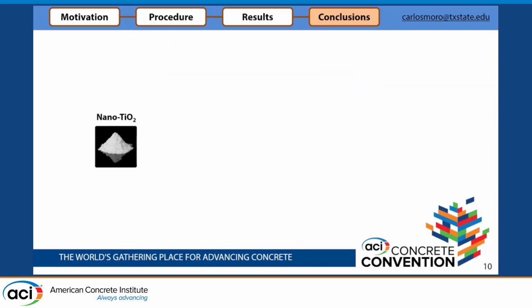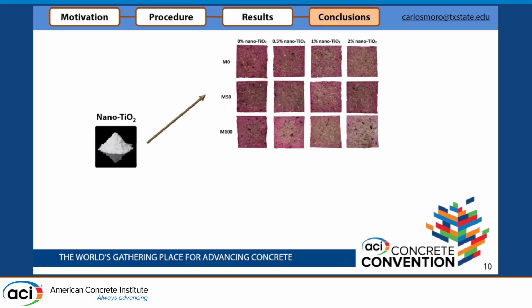Okay? But also, in one of our former studies, here I show the phenolphthalein test with different recycled aggregates. M0 means only natural aggregate, M50 means 50% recycled aggregate and 50% natural aggregate, and M100 means all recycled concrete aggregate, with different percentages of nanotitanium dioxide. In this test, we can clearly see that the carbonation is increasing with the use of recycled concrete aggregate, that is a well-known thing, but also with the use of nanotitanium dioxide. That means that maybe this is suggesting that nanotitanium dioxide can promote the CO2 capture.